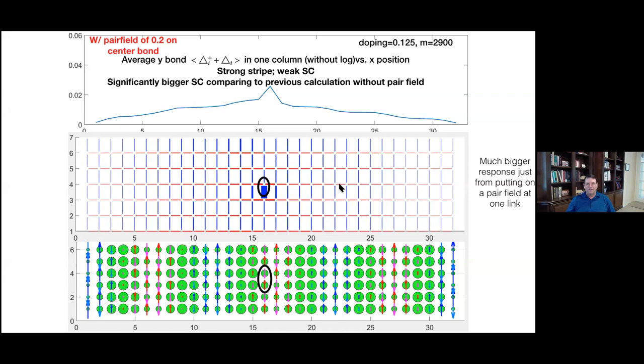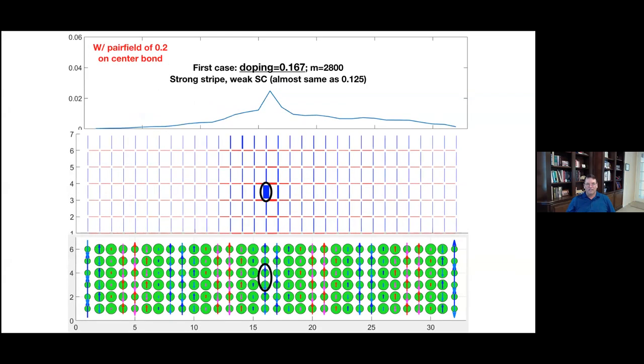Okay. So now let's look at a little bit higher doping. This might be pretty close to where you would say there's optimal doping in the cuprates. What's interesting here is that I'm going to show you three different results on essentially the same system. When we apply a pair field in the system, we have to do it in a grand canonical ensemble with a variable number of particles. So we apply a chemical potential, but we don't actually know how many particles we're going to get.